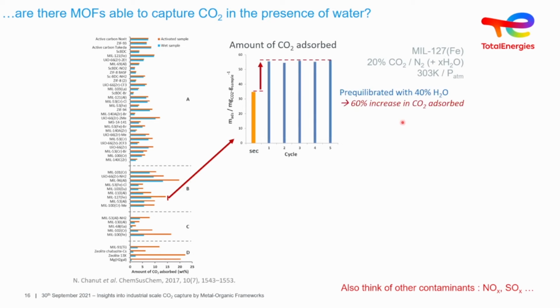MIL127 material. So if you carry out the adsorption over various cycles, so for the dry sample, we have the adsorption of a little bit, 35 milligrams of CO2 per gram. We have an increase as we increase the number of cycles. And this is in the case where we have pre-equilibrated in 40% water. So there's 40% water pre-equilibrated in the system, so quite a lot of water. But we still see an increase in CO2 adsorption. If we go to higher water amounts, then we start to see again a decrease in the CO2. But still, an interesting result.